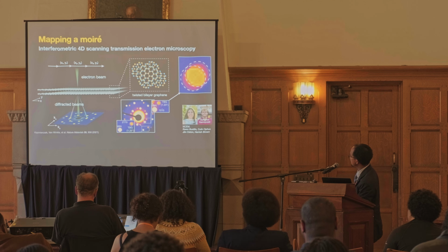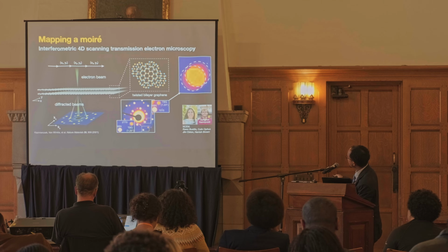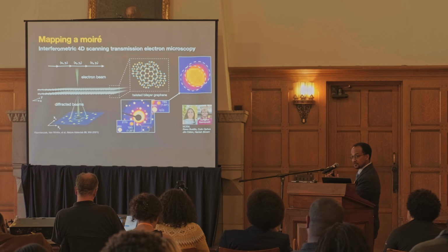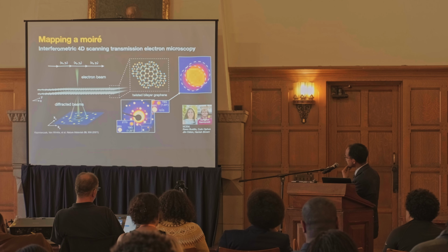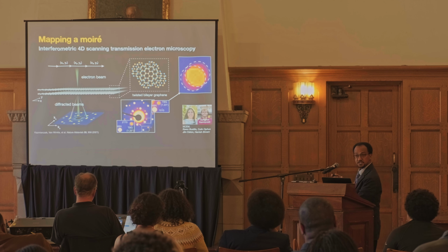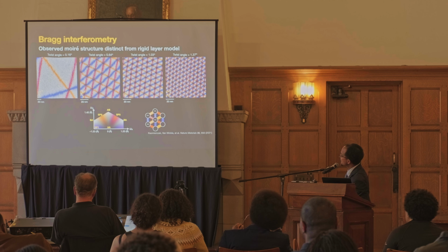You don't need to know all the details here, but what we end up doing is we look at how the beams that are nudged by each of those layers interfere with each other. Remember, an electron is a wave. We know that from 1927 or so. So they can interfere constructively or destructively. And if we take that information and process it in various ways, we can actually map the structure of these Moiré superlattices at different angles. We can make samples with different angles and we can map the structure.